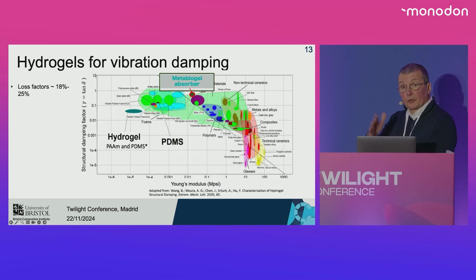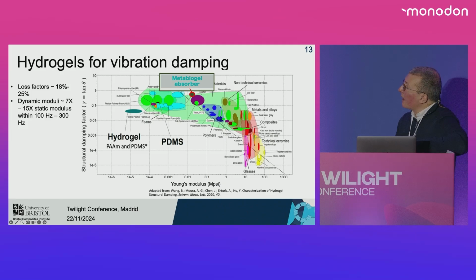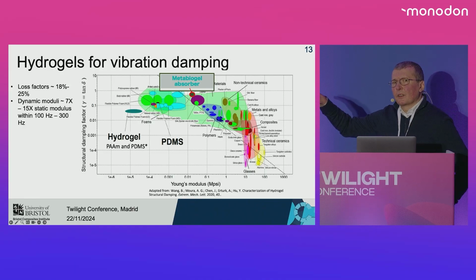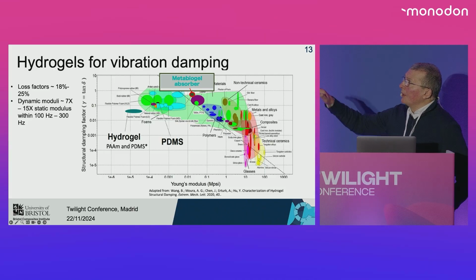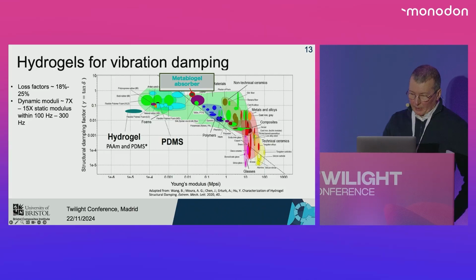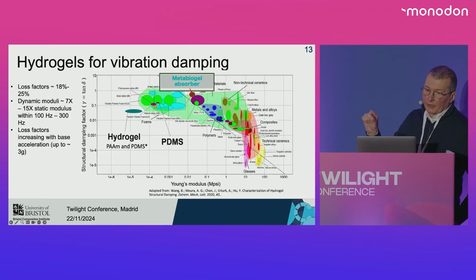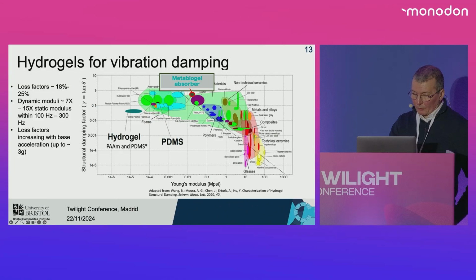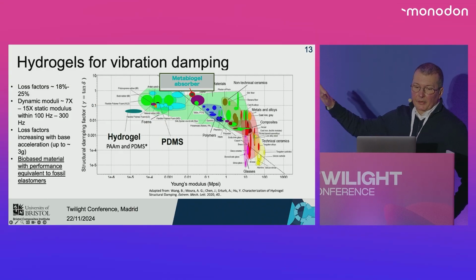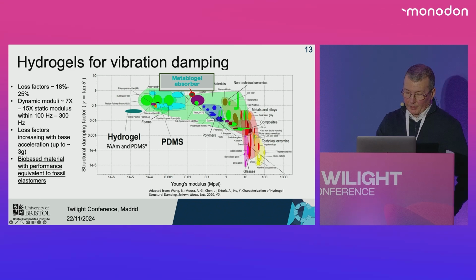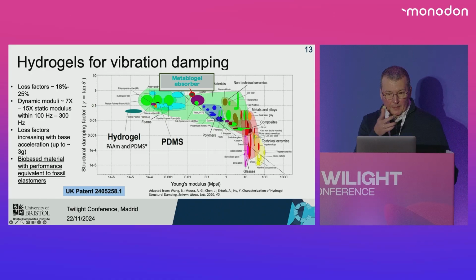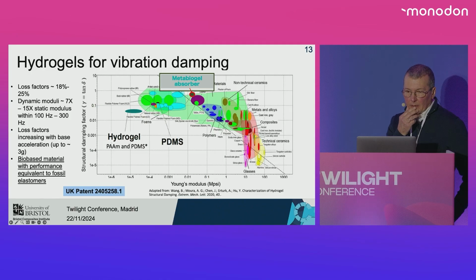and you use this composite to assess its vibration transmissibility properties, you obtain a sort of damping material with a loss factor between 18 and 25%, but quite staggering, a dynamic modulus which is between 7 and 15 times the static modulus within 100 Hz or 300 Hz. This is a frequency range that is actually quite difficult to handle for most of the fossil damping materials that are used on the market. And actually, the loss factor is increasing with the base acceleration. Quite interesting. We have done this test up to 3G. And in essence, it is a bio-based material with a performance equivalent to fossil elastomers. And we have a patent that is going international from April 2025.